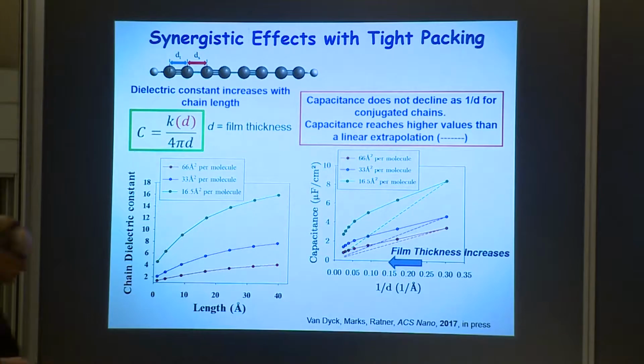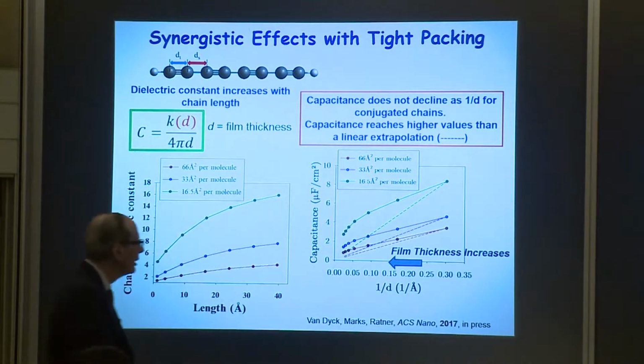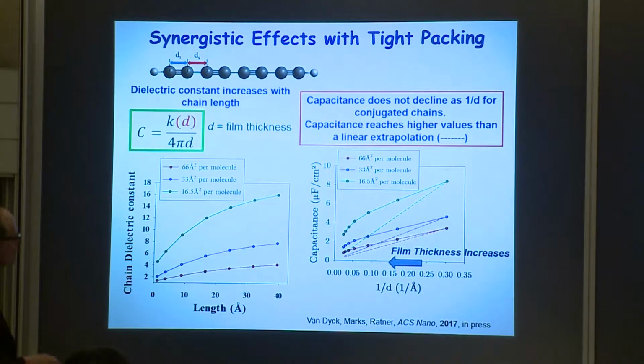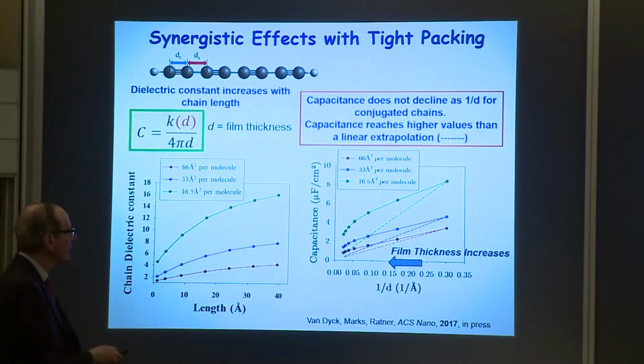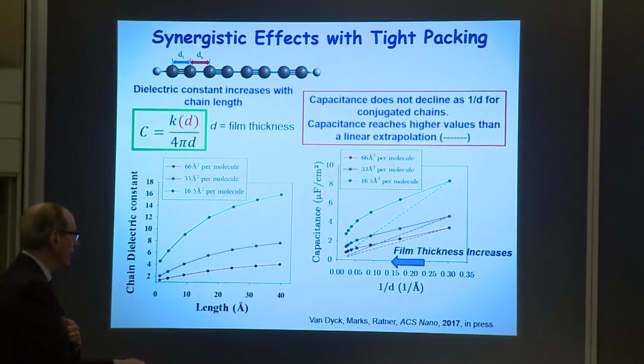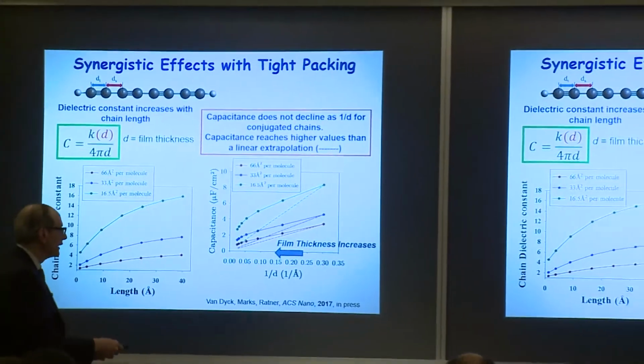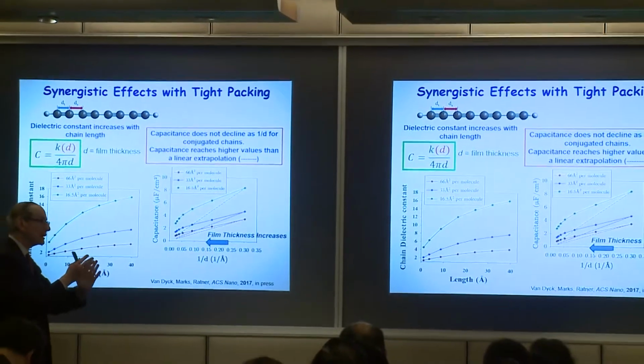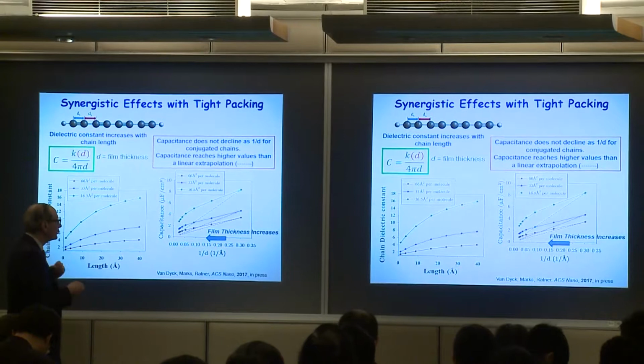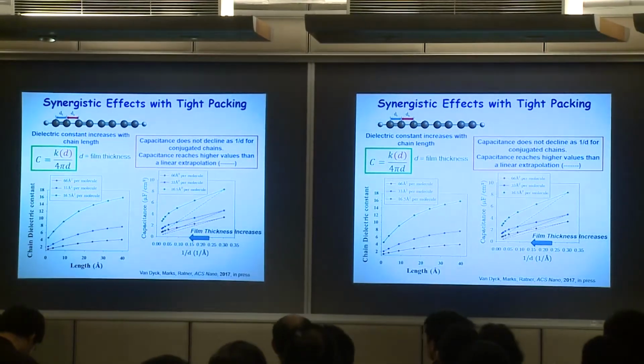Now, Colin Van Dyck came along, and he was a postdoc, and he said, what you really should be doing is take these molecules, and as you move them together, let the orbitals mix. And what you see here is really remarkable, and plotted the way a physicist would plot it. Very, very bright guy, but the capacitance doesn't have to be. So here's the dielectric constant of a chain and of these kinds of molecules. And what you see, it's not linear. In fact, when you get the chain longer and then you pack them tighter and tighter until you get down to the van der Waals radius, it becomes nonlinear. And you get higher capacitances than you would normally expect.